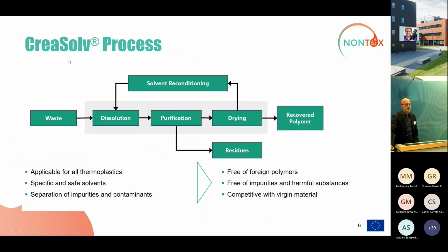Okay, CreaSolv. CreaSolv is a process where we bring waste in contact with a solvent. The solvent is then capable of physically dissolving the target polymer. It is not a degradation. We just mix solvent and polymer, and the macromolecule is now in a dissolved phase. After that, we can purify from the dissolved polymer all the non-target polymers. They have not dissolved and they can just be filtered off. And we can further purify them from co-dissolved materials like flame retardants, small particles of fillers and so on. And this is exactly what we've done.